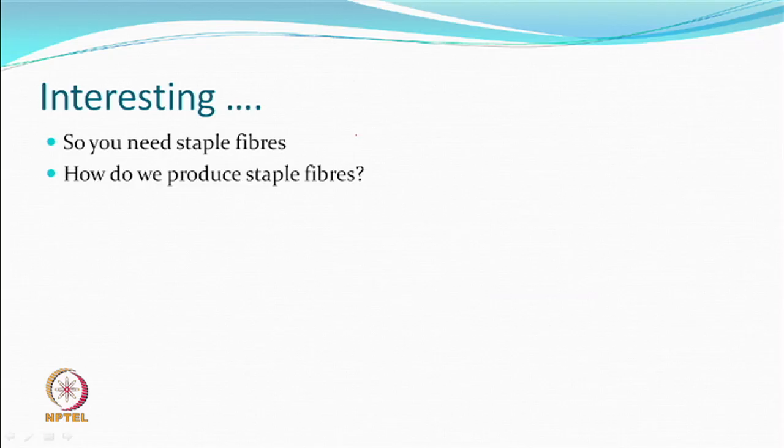So, now this type of material is called a biconstituent yarn. So, you need staple fibers. It is not like you have a shrinkable filament yarn and a non-shrinkable filament yarn and you say look, now come together. It has not worked. So, you need blending and twisting. Okay. And so, it is a staple fiber based thing, all right.